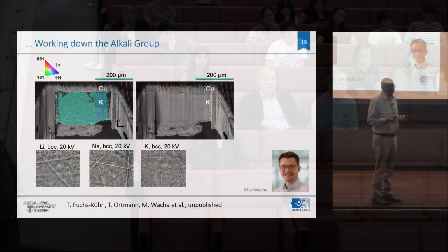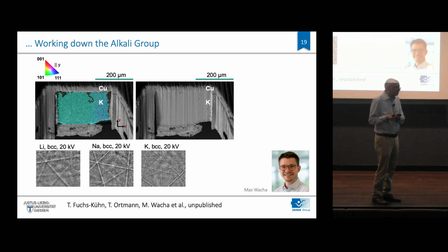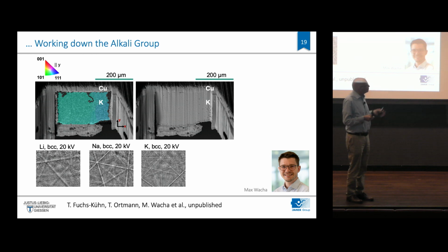Yeah, this is something we already discussed. There is so far only a very small number of works. There's one from Shirley Meng. They say they see preferential orientation, but with very small statistics, only a few grains. It's difficult to make proper statistics. We have meanwhile managed to make millimeter-wide images where we have 150 grains analyzed. We don't currently see too strong a preferential growth. I would not exclude it anyhow.